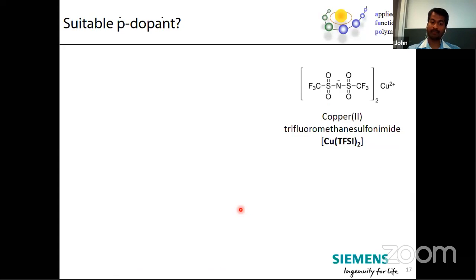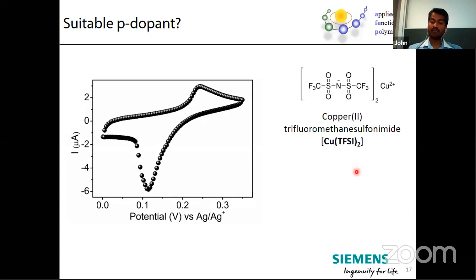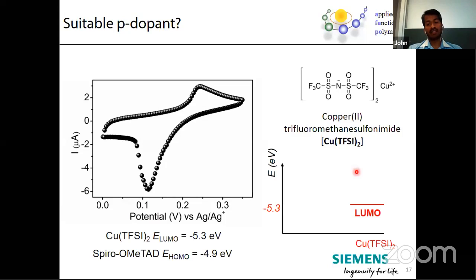While we were looking for the dopant, we received a copper complex from Siemens at that time. The copper complex is known as copper trifluoromethyl sulfonamide, and in short, we say copper TFSI. So we wanted to see whether the copper TFSI could actually dope our spiro or not. For that, we need to know the redox potential of copper TFSI, as I mentioned in a couple of slides before. So we did cyclic voltammetry. It's a very fundamental experiment, and we calculated the potential, or let's say the LUMO level of the copper TFSI, which lies at around minus 5.3 electron volt.